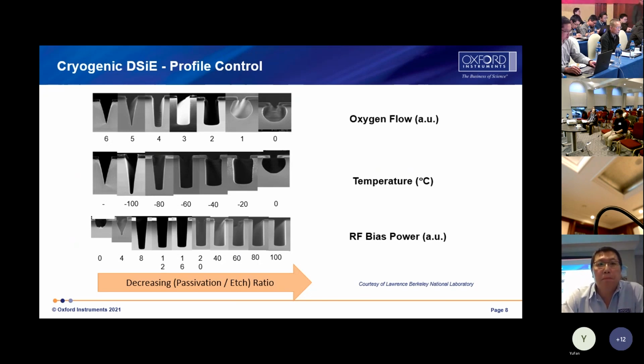This is process trend data we studied with a colleague at Oxford Instruments. There are three key parameters: oxygen flow, temperature, and RF bias power. We can control the profile from the left-hand side, a positive sloped profile, to the middle, a vertical profile, and then undercut and re-entrant profiles. The three parameters can usually compensate each other. From a positive profile to a vertical profile, we can reduce the oxygen flow, or increase the table temperature, or increase the RF bias power.